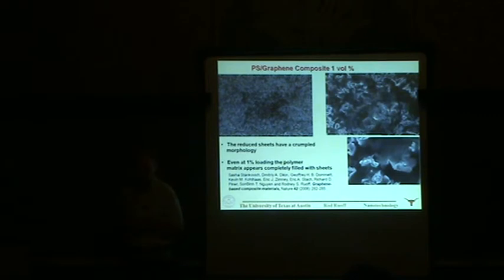rubber-like or elastomer system. You're probably aware that percolation limit for spheres is around 40%. So if you put carbon black into a rubber material, small spherical particles about 10 nanometers in diameter, you can rigidify the rubber. You can push its stiffness up significantly, but you embrittle it also, because you have to add so much material to get it to be stiffer. And perhaps also you want to imbue it with electrical conductivity at the same time.